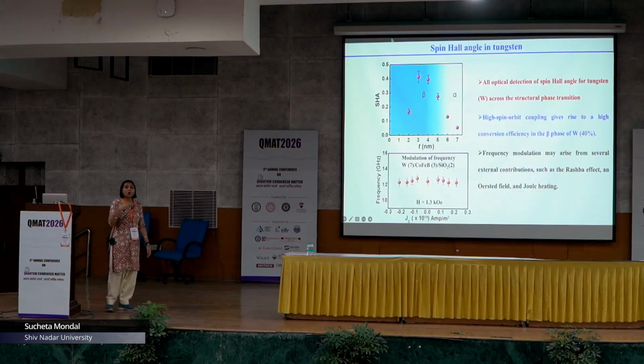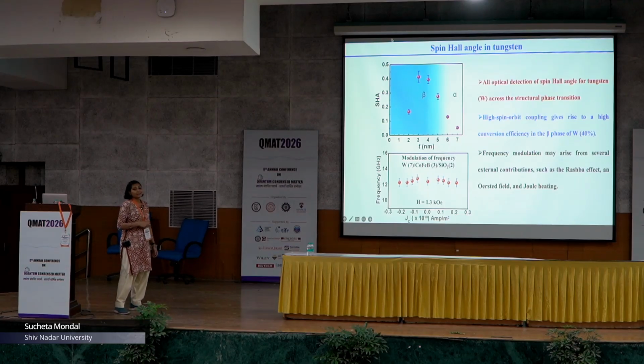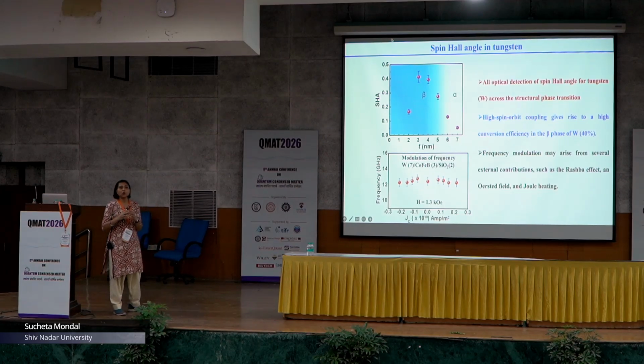After getting the modulation, we have used the previously described formula to extract the spin Hall angle. Now we have plotted our spin Hall angle for different tungsten thickness, and we have this non-monotonic change. Now beta tungsten has higher spin orbit coupling, that you know, but why is there a drop at this moment, at this thickness?